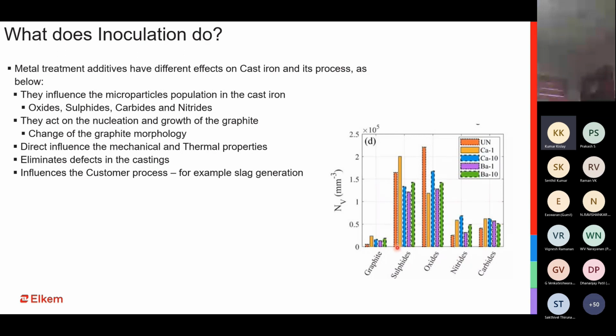Then whether it takes the shape of a flake or that of a nodule would depend upon whether you introduce magnesium into the system or not. So thus, it acts as a nucleating site, it promotes the growth of graphite, and also ensures that because we have a control on the amount of sites, we are able to control the morphology of the graphite. How? I'll speak about it later.